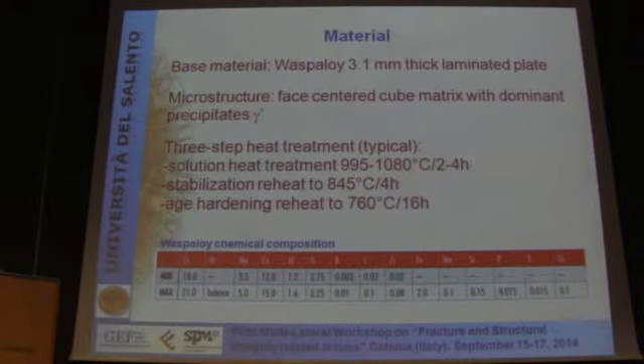The microstructure is a face-centered cubic matrix with dominant precipitate gamma prime. Generally, this material is used after a three-step treatment, that is a solution treatment, a stabilization treatment, and an age hardening treatment. Temperature, time, and cooling conditions are varied to obtain better performance in creep strength or fatigue strength.